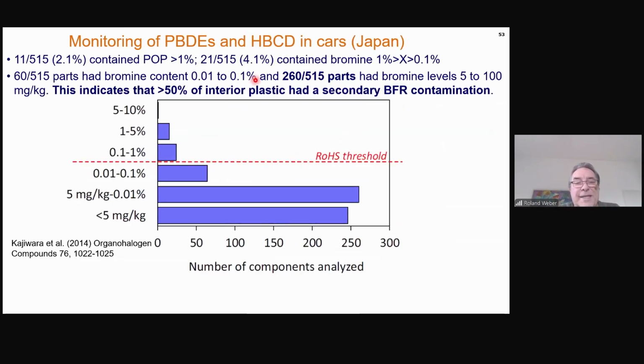What was also interesting was the low bromine contaminated samples. So you see that more than 10% had bromine content between 0.01 to 0.1%. And 260 out of 500 samples, this means more than 50% of the samples, had bromine levels of more than 5 ppm, 5 milligram per kilogram. This indicates that 50% of interior plastic had a secondary contamination with brominated flame retardants. It is not clear if this mainly comes from recycling or partly comes from secondary contamination indoor. This means PBDE can evaporate, for example, from the seat textile and then can deposit on other plastics. And over the years, this can increase to levels of more than 5 ppm.